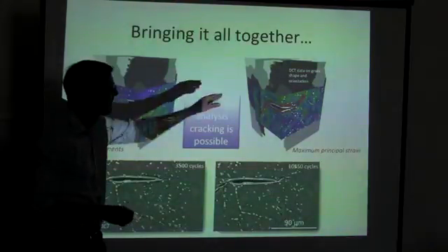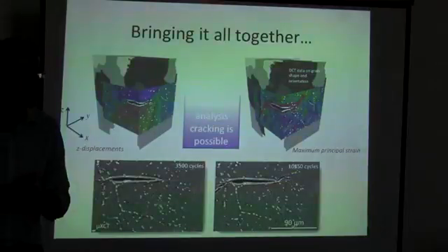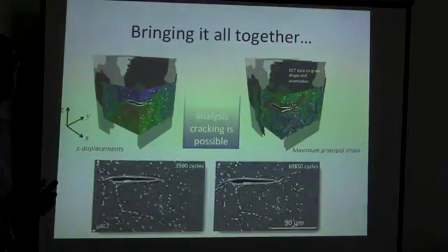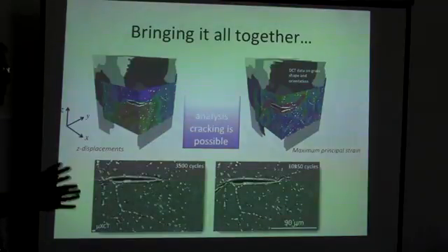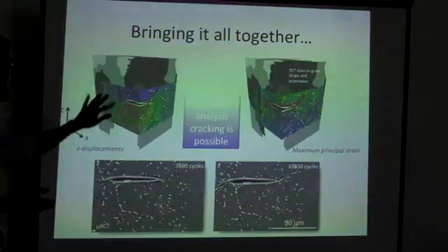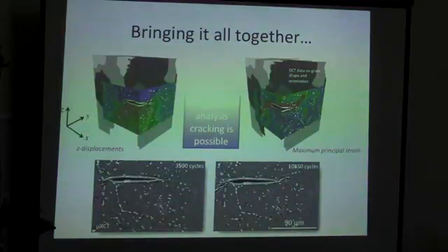On the right, just for visualization, is the strain field. My preference when using image correlation, any form of image correlation, is I'll use strain for visualization, but I'll always go back to the displacement field. The displacement field is the data. The strain is usually much noisier, it's just the gradients, and some of the ways the software calculates strains are not necessarily the best tools for doing it.